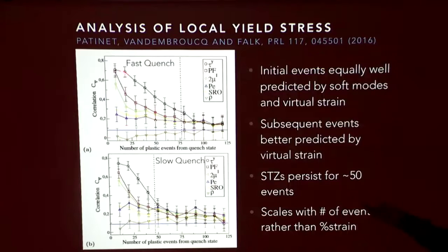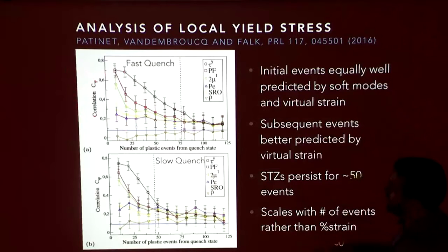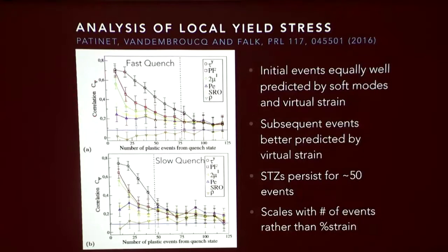We've quantified that. This is a graph of the correlation between the structure as measured in the original as-quenched material and the places where we get deformation. Here we're comparing different measures of the local structure, different attempts to measure where the system will deform. Black is the local yield stress, that's the measure I was just showing you.